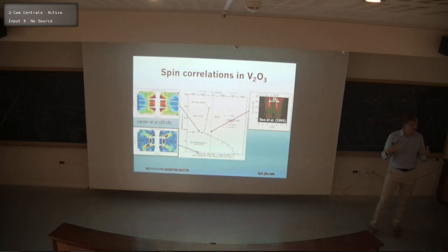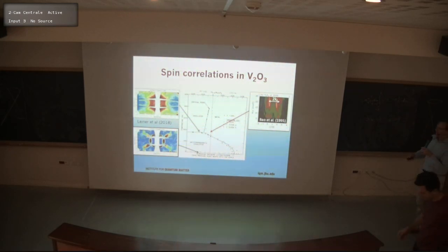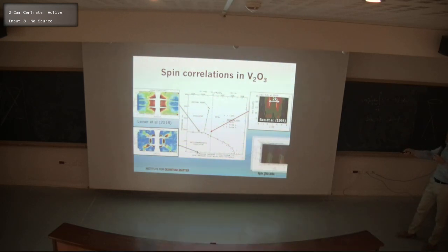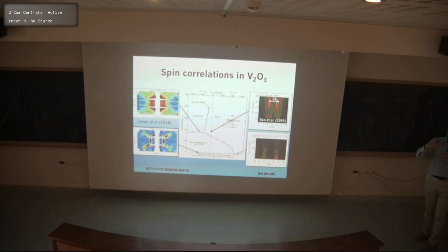associated with that Fermi wave vector. And then eventually, if you cool the system down, you have to go all the way out here. Then these correlations, which are related to a nesting kind of instability, eventually give rise to a spin density wave, and these are very sharp. And at this point, you're kind of dominated by the correlations imposed by the fact that you're in a metal. So our impression is that somehow the materials that do show this phase boundary happen perhaps to be highly frustrated, and that's our impression. And then I wanted just to conclude.